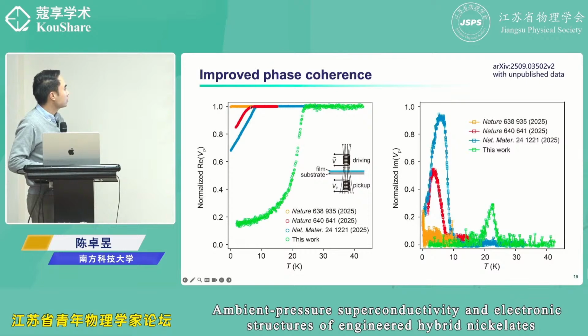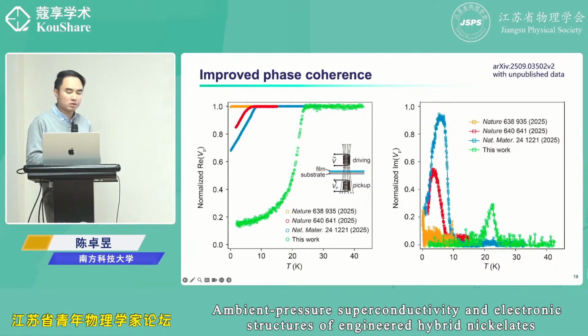So this is the first report from Stanford. This is our first report, and this is the second report from Stanford, and this one is our most recent data. So you can see the diamagnetism is saturating approaching zero temperature, and also it's quite close to zero already. This discrepancy may be coming from the leak of the magnetic field from the side of the film, because the film is 5 by 5 millimeter, and this thing is about 2 millimeter. So there is still some magnetic field escaping from the side of the film.